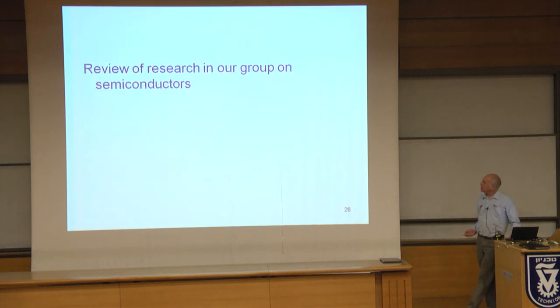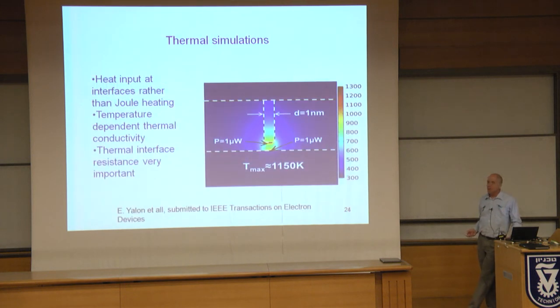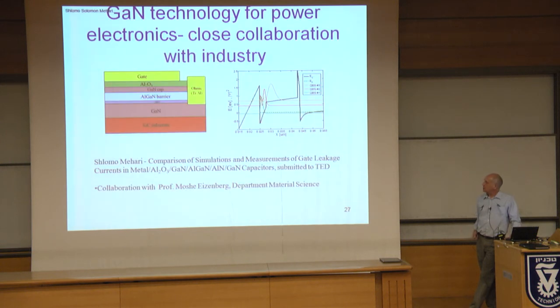Yes, I promised to mention names. So Elam Yalon is doing the work on the filaments in insulators. He's a student in charge of most of the results, all of the results I've been showing. And Shlomo Mehari is working on gallium nitride. What we're trying to do here is actually to simulate current through the aluminum oxide gate insulator. We've got the quantum well here in the gallium nitride cap, so it's not so easy to do the simulation and get the correct leakage and to find out whether leakage is due to tunneling or maybe to some trap-assisted tunneling. That's important to evaluate to understand the leakage current through this gate stack.